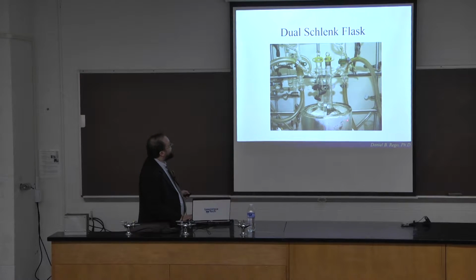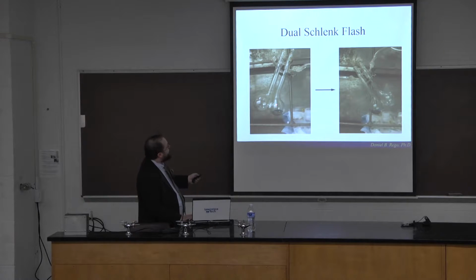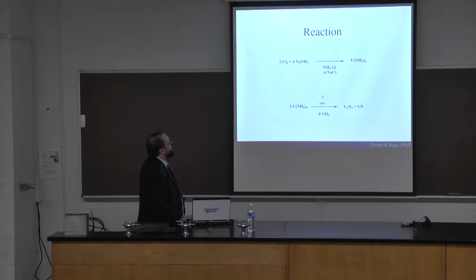Now to do this, I actually invented this apparatus here. It's a dual Schlenk flask. So this is under a vacuum or argon on a Schlenk line. I have two of them set up, and they're only connected at the bottom by a glass filter frit. And basically what I can do is do the reaction here, and then filter it through here by simply twisting it while keeping the entire thing submerged safely in a cold bath, so I don't end up heating a liquid next to a material which is tens and tens of degrees higher than its boiling point. It was just a question of safety.